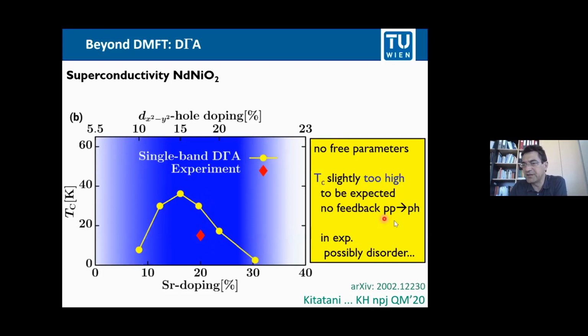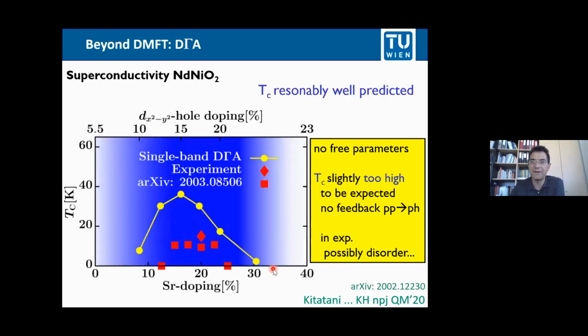And we think it's higher because of this feedback of the particle-particle channel. If these fluctuations get larger, we think they will suppress the antiferromagnetic fluctuation in the particle-hole channel. And therefore, in the theoretical calculation, if we improve our method, we will go down a little bit. On the other hand, in experiment, you can also have all kinds of disorder effects, for example, that are known to reduce the TC. Okay, that was our calculation, and then one month later, the Hwang group and also the Ariando group measured the phase diagram, and it's that one.